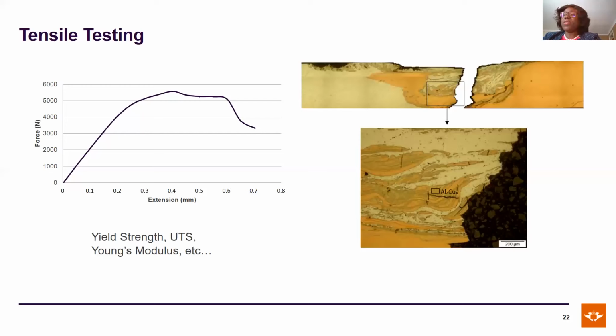Now, for welds generally, this particular weld I've shown you on the right-hand side, if you look at it very closely, you will observe that this particular weld has fractured just in the TMAZ, the thermomechanically affected zone. When welds are characterized and can be given a thumbs up as good, it is expected that the weld should fracture at the heat affected zone, completely outside of the stir zone and also outside the TMAZ, which is usually an indication that there's a good bonding of the two materials that have been joined.